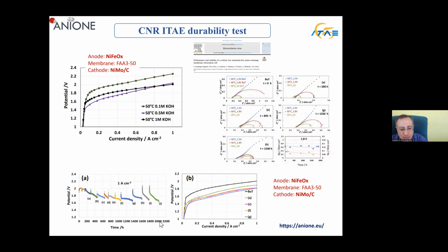These are tested to 2,000 hours, but there's a new drawback, the reversible losses. You can see some reversible losses during startup and shutdown. So the dynamic behavior of AEM electrolysis is not as good as PEM electrolysis. We also need to recirculate some KOH to enhance the conductivity a little bit, 1 molar KOH. When we decrease it to 0.1 molar KOH, you can see there is a loss of efficiency and an increase of cell voltage. This is another important aspect.